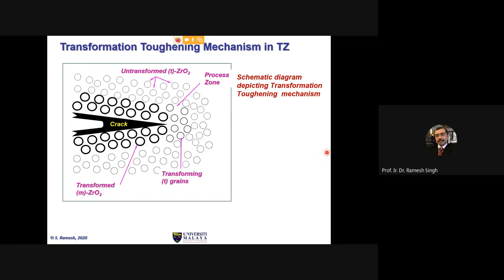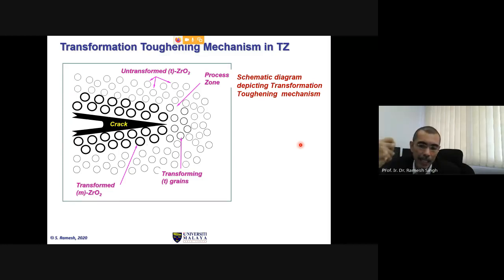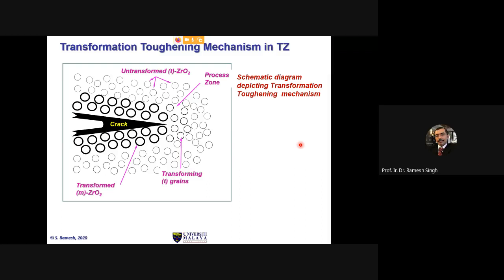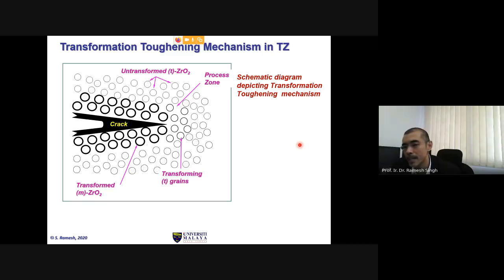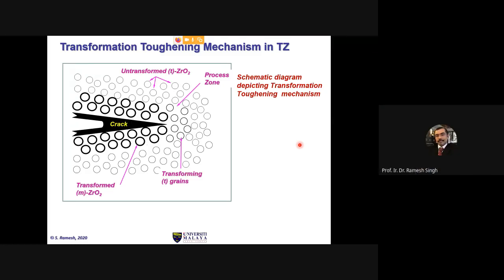Right, in terms of zirconia, it has a unique healing ability. When there's a crack trying to propagate through the material, it actually arrests the crack. So we call that transformation toughening. And this is only unique in tetragonal zirconia. All right, and we capitalize on this behavior of this material. Remember I explained just now, part of our studies in mechanical engineering, we learn to understand behavior of material, and this is where we apply it in our further studies, like in our PhD studies.